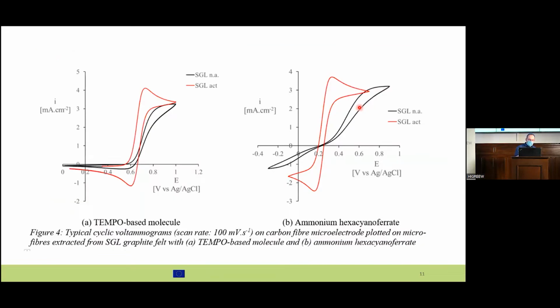So here is how it looks. Again, it is cyclic voltammetry. I do not enter too much into the details, the voltage, the current. What is important now is that we can clearly differentiate the activated versus the non-activated, here for the hexacyanoferrate, one of the electrolytes we use in HIGREEW. This is the non-activated, this is the activated. The displacement of this curve towards the left is an indication that the kinetic is increased. And this is the case for the two electrolytes tested here.